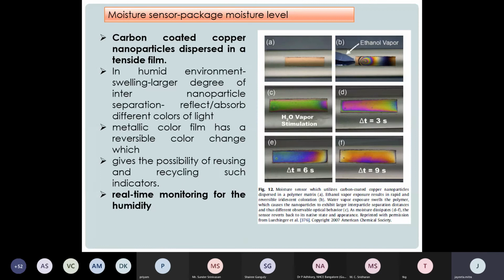Moisture sensor: to check the package moisture level, carbon coated copper nanoparticles dispersed in a tenside film are used. In a humid environment, swelling causes a large degree of inter-nanoparticle separation, which reflects or absorbs different colors of light. A metallic color film has a reversible color change, which gives the possibility of reusing and recycling such indicators. So real-time monitoring of the humidity is possible. You can see how the color has changed with time.